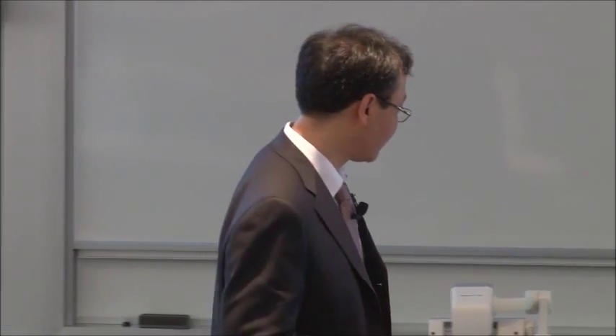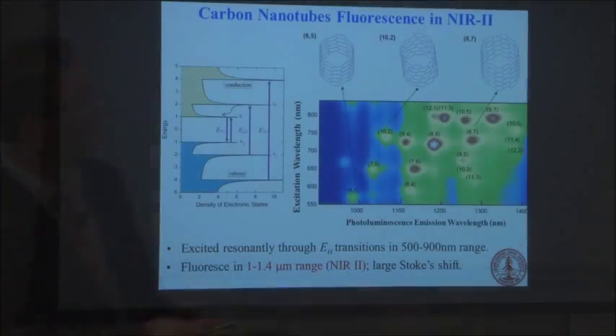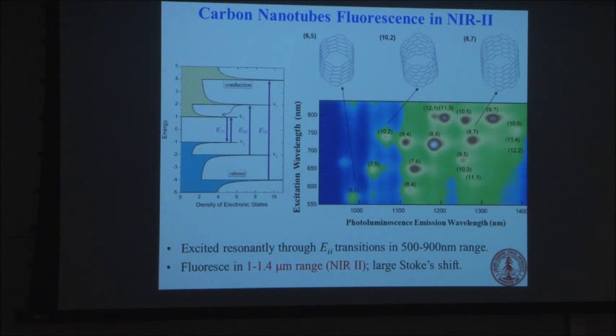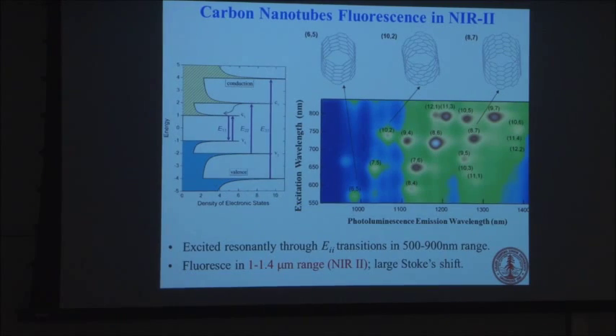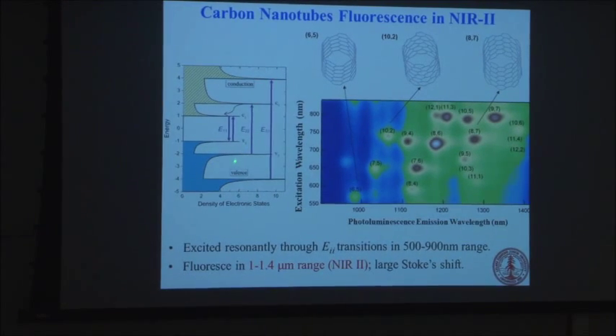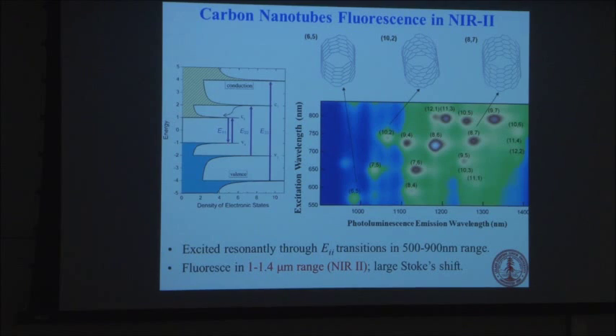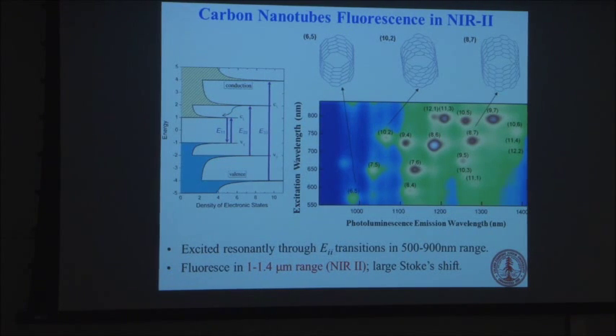They are one-dimensional systems, and they have a kind of band structure which is characteristic of 1D systems. What that means is that you have these Van Hove singularities, and you can have optical transitions between these levels, very much like in molecules. And then you can also have light being emitted from these systems. In this case, you excite between these higher energy spacings, and then they emit at smaller energies.